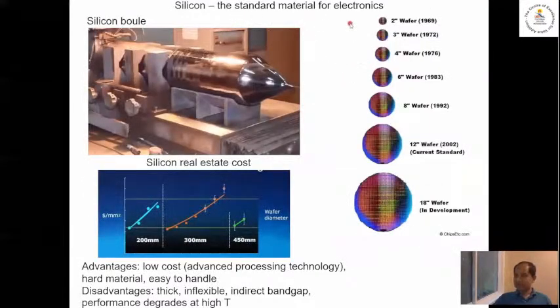The standard material for electronics has been silicon for a long time. And so here we have a picture of a silicon boule. This is a huge piece of single crystal silicon. It's 12 inches like this, 18 inches like this. And the size of this boule has been getting bigger with time. So the idea is that they take this boule and cut it into slices, and then they polish the slices, and then on these slices they make chips, and then they break them up and put them in packages, which appear in our devices.